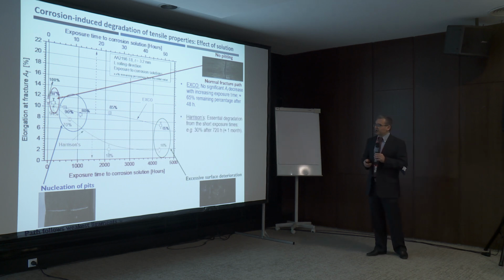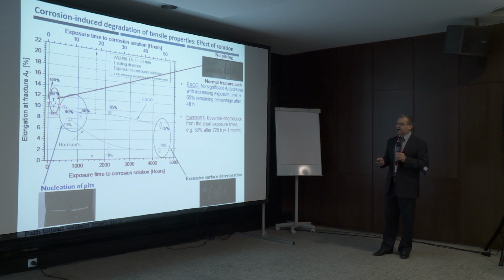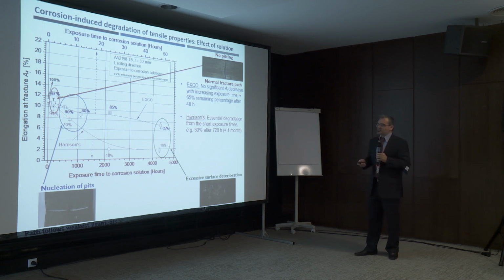But how does the story go with the Harrison one? For the Harrison one, you can see an inclined, linear degradation of elongation at fracture for the small exposure hours, up to 720 hours. And then you have extreme deterioration due to localized corrosion.